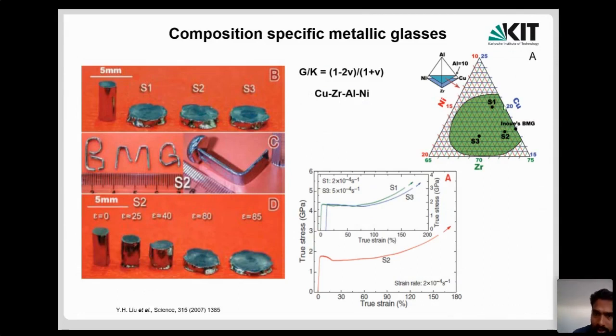So what they have done is they have taken this composition copper, zirconium, aluminum, nickel, and they have identified three compositions where they thought the Poisson's ratio is quite high. And from those compositions, they have tried to do bending of the samples like here. They have done compression. You see that the material has become absolutely flat. So this is quite an interesting observation. And they have showed that the plasticity is enormous.